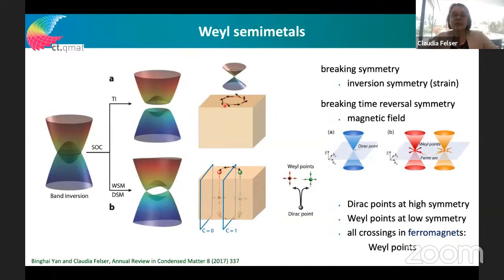Now you can imagine this is my crystal. It's an insulator in the bulk because we have this nice band gap. This can be bismuth telluride or bismuth selenide. And then on the surface we have this nice Dirac cone I showed you in bismuth telluride. The surface state, you might remember, is now shown in this 3-dimensional visualization, and here you even see the spin structure of the surface state. So my crystal is insulating in the bulk, but has this very beautiful surface state.